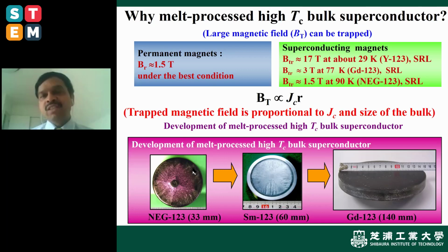That is a liquid oxygen temperature, not liquid nitrogen temperature. All this depends upon the JC, the critical current, and the sample size. So in this process, we started from 2 mm and reached 140 mm bulk superconducting magnets. And we also work to improve the JC values.